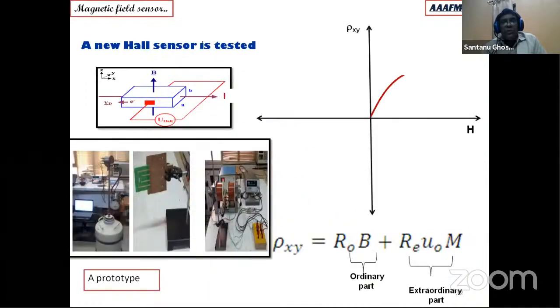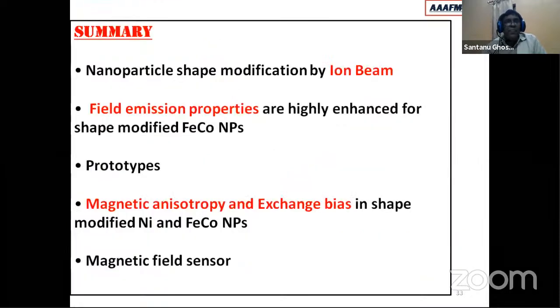And we have also made a prototype based on these particles where one can see the out of plane resistivity varies with magnetization. This is a typical phenomenon of the anomalous Hall effect, and this is a much more sensitive Hall sensor, a magnetic field sensor, as compared to the normal Hall effect.